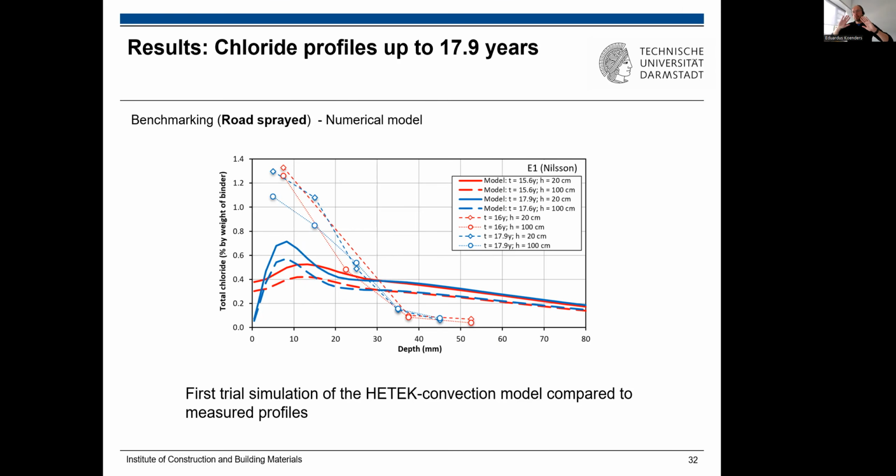The chloride load lasts only a few months, maybe 1 or 2 months, and with climate change it will become shorter every time. Then during the year you have the rain, and it can happen that many chlorides in the pores at the surface will be washed out. That's what he also took into account, and he did a very nice analysis. More details are in the book on whether you have to take that into account or not, all those details.